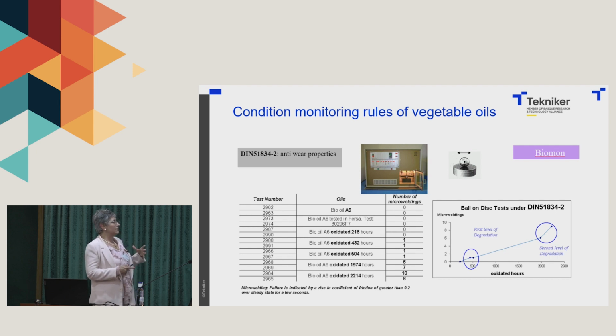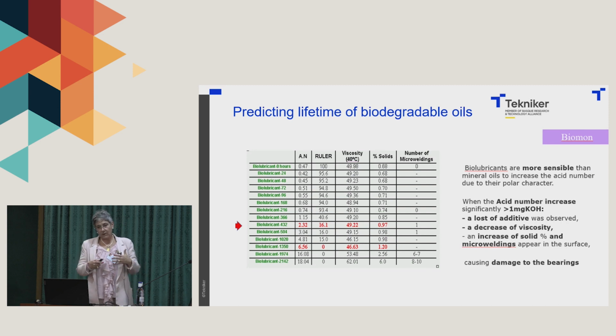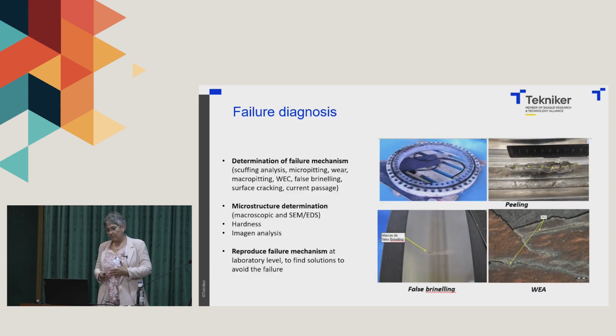Then it is important to control the oxidation evolution, because we accelerated the lubricants at the laboratory scale, and we saw that there is an interrelationship between the oxidation increase and damage. Then controlling the TAN number, that is the acid number, it is possible to control also the welding in the system. We saw that it is important to control that the acid number is not higher than 1 milligram KOH, because if this is higher than this quantity, then it could start welding in the component and damage the bearing and other parts of the component.